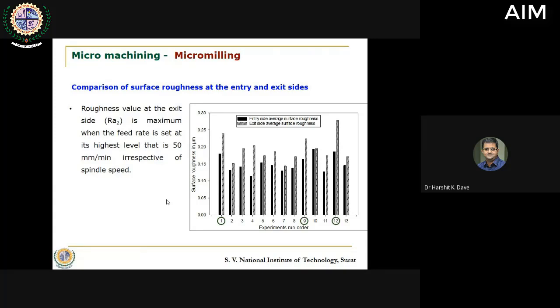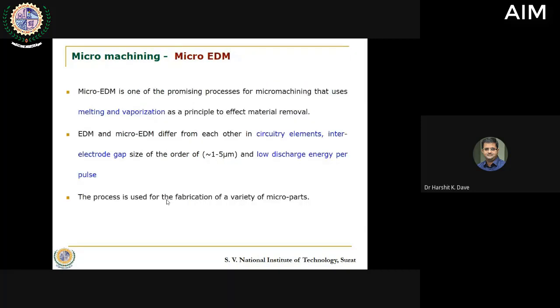When the feed value was maximum, we found that feed has the maximum effect. In these three particular cases, reading number 1, 9, and 12, the feed value was at 50 mm per minute, which was the highest selected value. So whatever be the spindle speed, when the feed increased, we observed that roughness increased. So feed is found to be an influential factor on roughness value at micro, sub-micro level instead of the spindle speed value.